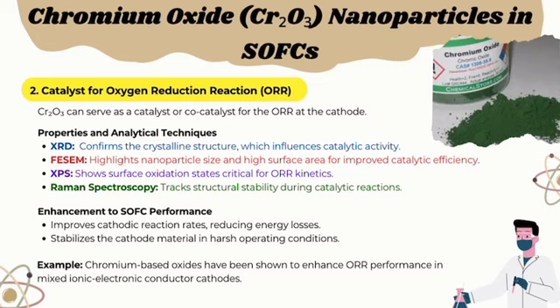The properties and analytical techniques used are XRD, which confirms the crystalline structure that influences catalytic activity, and also FESEM, which highlights nanoparticle size and high surface area for improved catalytic efficiency. XPS shows surface oxidation states critical for ORR kinetics, as well as Raman spectroscopy, which tracks structural stability during catalytic reactions. The enhancement to SOFC performance improves cathodic reaction rates, reduces energy losses, and also stabilizes the cathode material in harsh operating conditions.